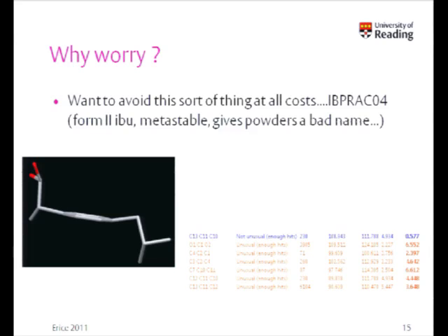Now, just to point out what this is, here's a carboxyl at the end. That does not look like any carboxyl I've ever seen or you will find in the database. This is a benzene ring here, so one might expect that that CC bond would come off in the plane of the benzene ring. So this structure is wrong, and you can tell it's wrong by performing a quick check on it.